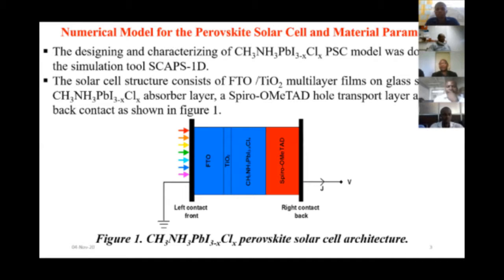In designing and characterizing methylammonium lead iodide doped with chlorine, we used the simulation tool SCAPS 1D, and the solar cell structure is as shown in our figure 1. It consists of fluorine doped tin oxide, TiO2 thin films on a glass substrate. It also consists of methylammonium lead iodide doped with chlorine as an absorber layer, spiro-OMeTAD as a hole transport layer, and silver back contact as shown in this figure.